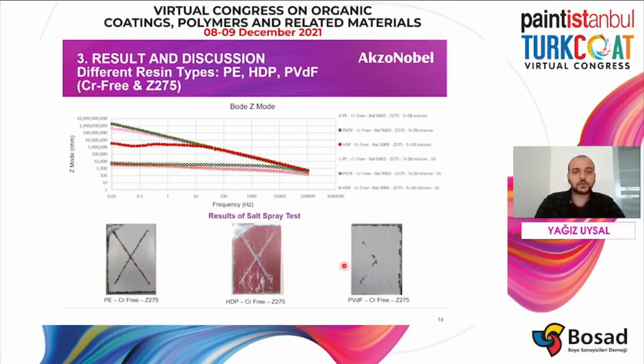Here we can continue with our top coats. We have three kinds of resin: PVDF, polyester, and high durable polyester. All of them are treated with chromium-free pretreatment and primer, and they have a zinc layer of 275 gram. All of the samples tested in this study are obtained from a coil coating line. Panels are taken and measured in the spectroscopy, and then they are tested in an accelerated corrosion test cabin for 1000 hours.